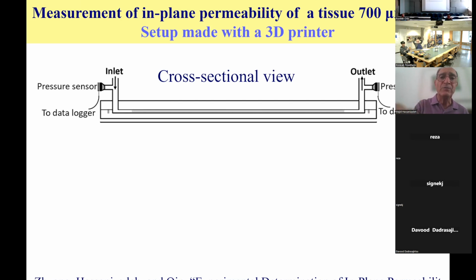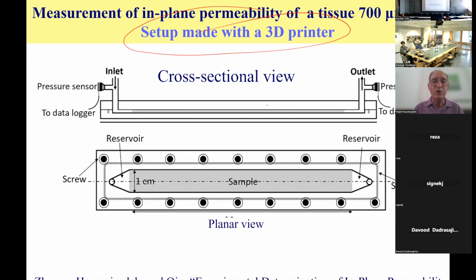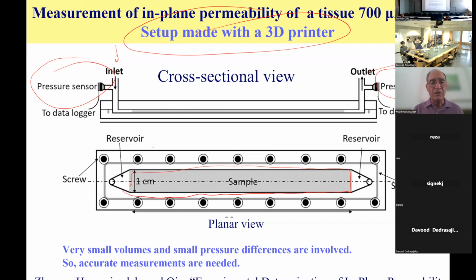So we made a setup using a 3D printer, where we created a very small indentation into a sheet of plastic. And then we could put our sample in there; this is the top view. Then we injected water, and also gas, and measured the inflow pressure and outflow pressure. These are small pressure differences. We also measured the amount of liquid that went through, and therefore we were able to measure permeability. But as I said, we deal with small volumes and small pressure differences, so you really need very accurate measurements.